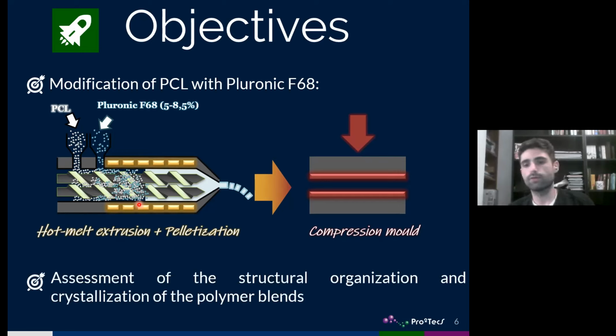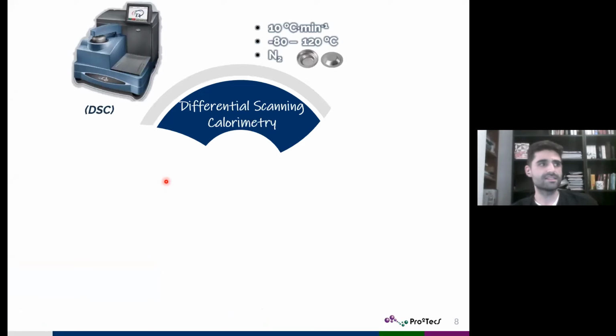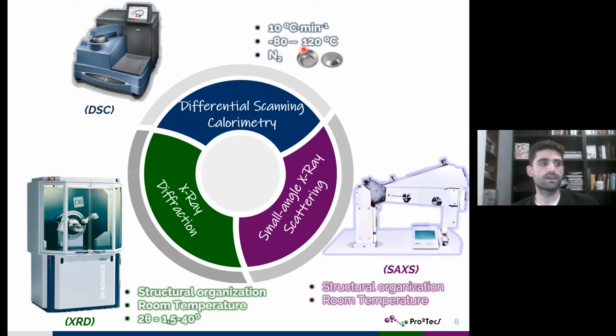To do all of that, we applied the following experimental techniques. First of all, we analyzed their thermal properties by means of differential scanning calorimetry. We applied this analysis under nitrogen atmosphere, conducting heating and cooling cycles within the temperature range from -80 up to 120 degrees Celsius. Then the structural organization of the obtained polymer blends was studied by both small angle X-ray scattering and X-ray diffraction, both conducted at room conditions.